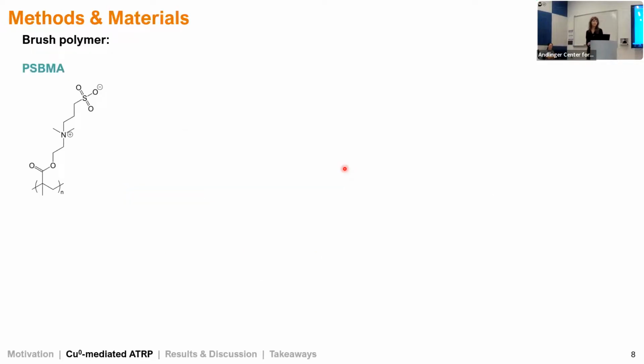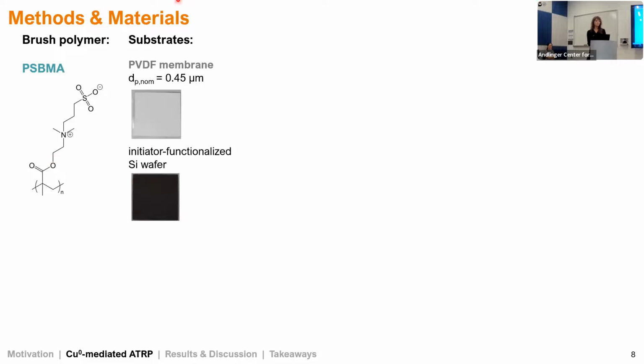So I'll just briefly introduce our methods. I'm going to show you results for polymerization of polysulfobetaine methacrylate brushes. This is a zwitterionic material that's been shown to have very high fouling resistance. For substrates, I'll show you results for modification of this microfiltration PVDF membrane, as well as for brushes grown from initiator functionalized silicon wafers, which allows us to characterize brush properties using ellipsometry.